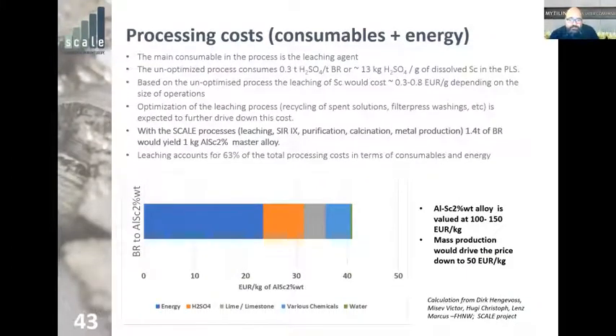Is this a viable option? Okay, so these are very preliminary numbers, but we managed to take down the acid needed for this process all the way down to 0.3 tons of sulfuric acid per ton of bauxite residue. That's about 13 kilograms of sulfuric acid for each gram of dissolved scandium in the PLS. So the cost of the process is driven mainly by the cost of the sulfuric acid and the cost for heating up the solution to 85 degrees.